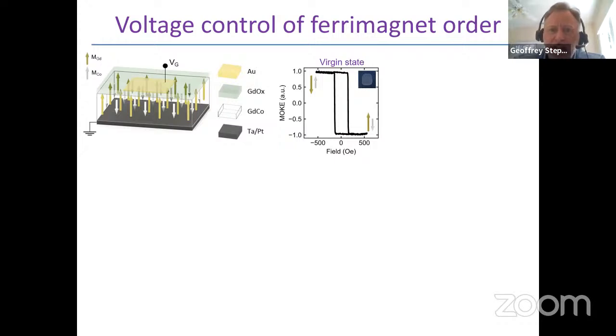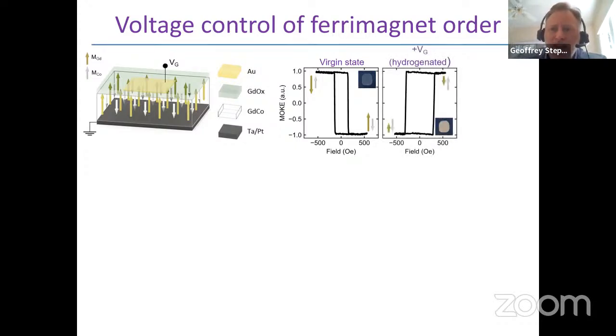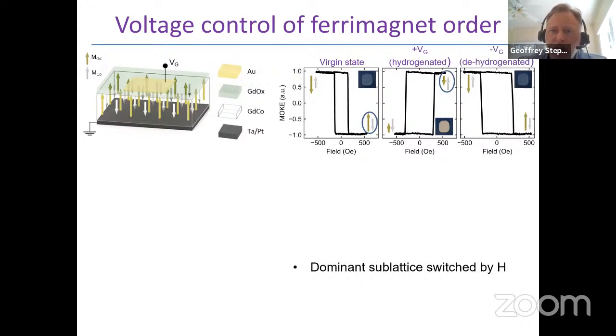And so in the virgin state, we measure a particular polarity of the MOKE loop. The absolute polarity is not important here, but the relative polarity is. When we gate this structure, so we hydrogenate it, the polarity inverts. And so that means at positive magnetic field, in one case, the cobalt is pointing up. In the other case, the cobalt is pointing down. And since at positive magnetic field, always the dominant sublattice will point parallel to the magnetic field, that means by gating it, we've changed the dominant sublattice. So we've driven it through compensation. And we can reverse that by applying a negative gate voltage to pull the hydrogen back out of the film.